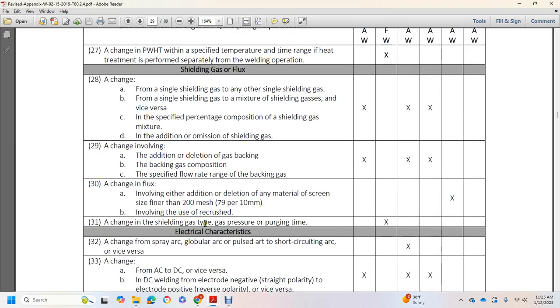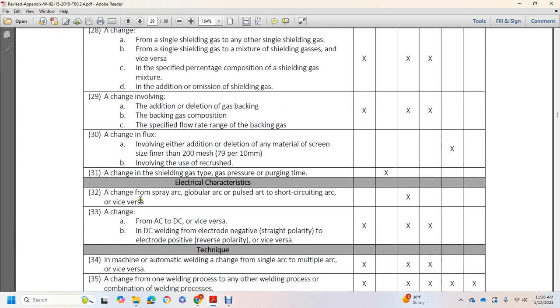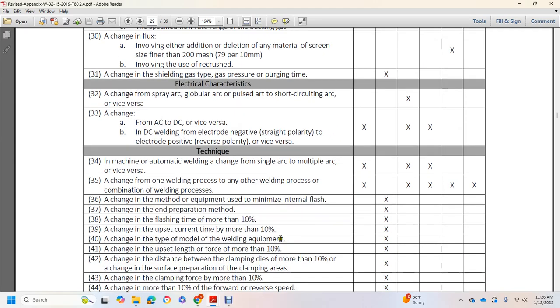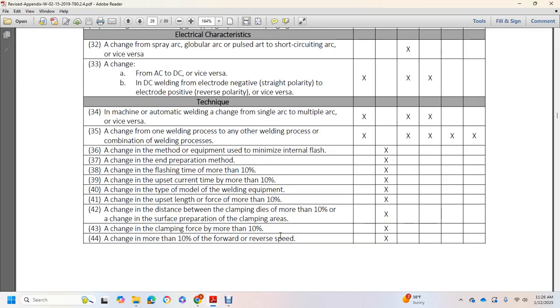31. A change in shielding gas type, gas pressure, or purging time. Electrical characteristics: change in spray arc, globular arc, or pulse arc, short circuiting arc, or vice versa. Change from AC to DC, vice versa. DC welding electrode negative straight polarity to electrode positive reverse polarity, vice versa. Technique of machine automatic welding: change from a single arc to a multiple arc, vice versa. Change from one welding process to any other welding process or a combination welding process.